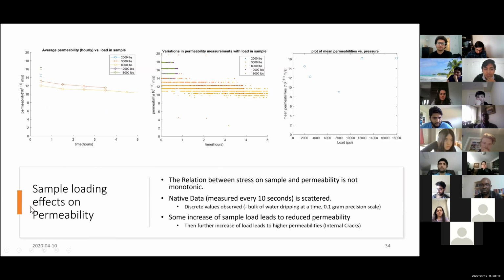So now I wanted to look at the effects of sample loading on permeability. In terms of effects of sample loading, we can see from this graph, this is the average permeability value. Since we can't really observe this, this is the variation in permeability observed every 10 seconds. So here we can see that this yellow 8,000 pounds value is the lowest. And this graph calculates the hourly average.